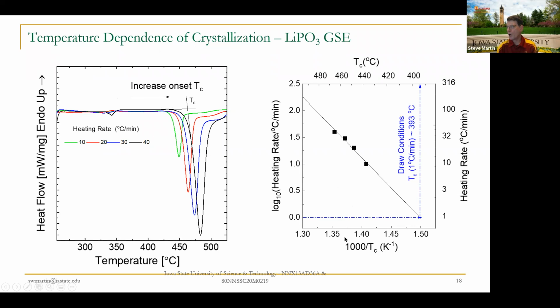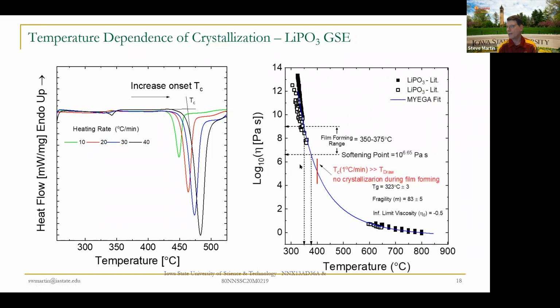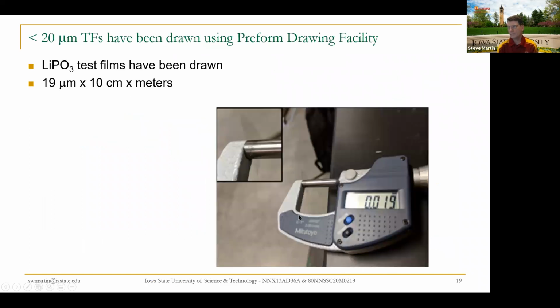I apologize for going into all the details here, but we simply extrapolate this out to where our draw conditions are. About 1 degree per minute. We heat it very slowly, and that gives us our draw temperature. Gives us our crystallization rate at our draw temperature, so we know where we're at. And then we can plot that here, our 400 degrees. And we say, yep, our draw temperature is at a lower temperature than our crystallization temperatures. Therefore, we can draw without the glasses crystallizing, because if they crystallize, of course, then we can't draw them into thin film.